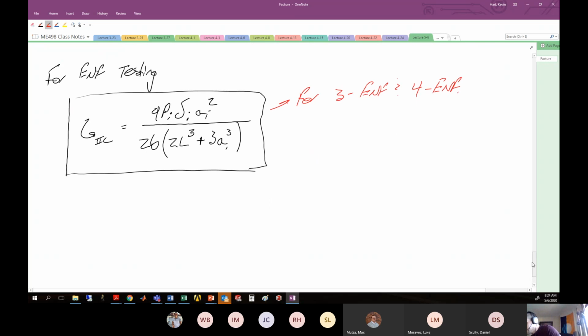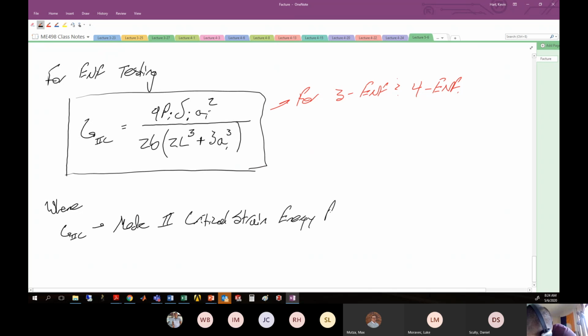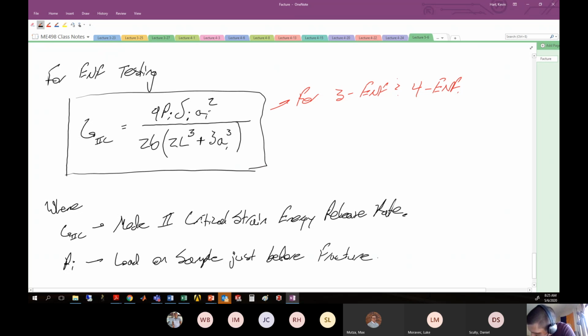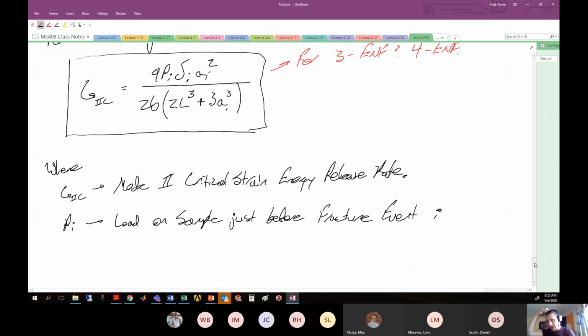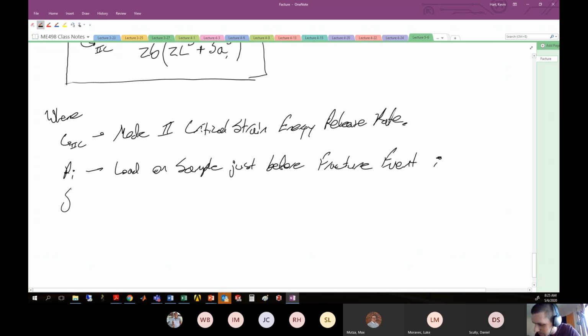All right, so let's explain what these variables are. Obviously, G2C is the mode 2 critical strain energy release rate. It's what we're getting after with this new geometry and this new type of test. P_I is the load on the sample just before fracture event I. Again, we're going to have these discrete failure events. We're assuming a stick-slip behavior. And delta_I is the displacement of the crosshead just before fracture event I.